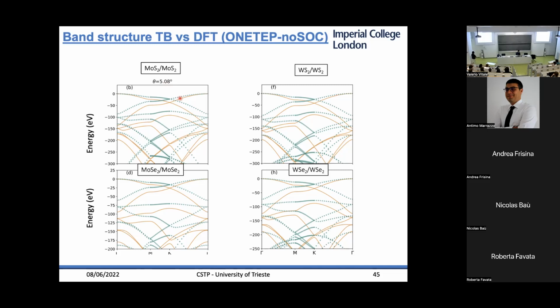But there is an issue where you have a system with different lattice constants, and then you twist. Then you have to introduce some strain on either both layers or one of the two layers to make it commensurate. We are not so optimistic on the hetero bilayers compared to the homo bilayers, because in the homo bilayers we can have these exactly commensurate cells.